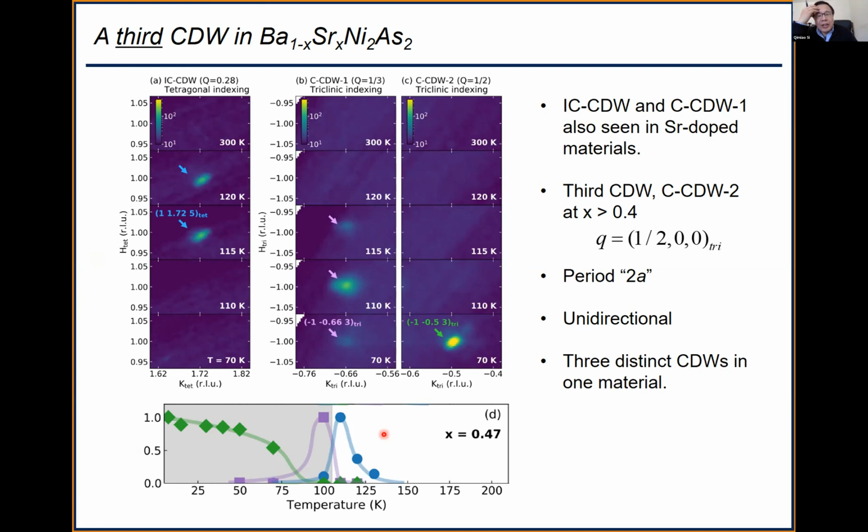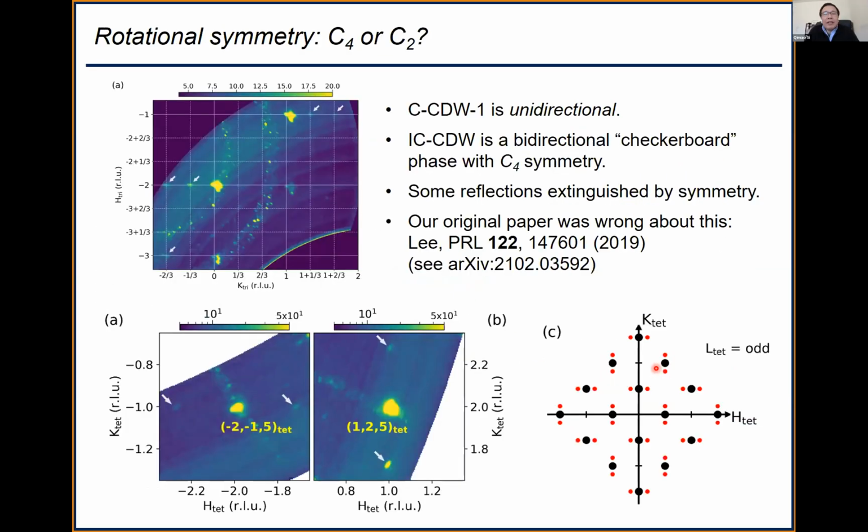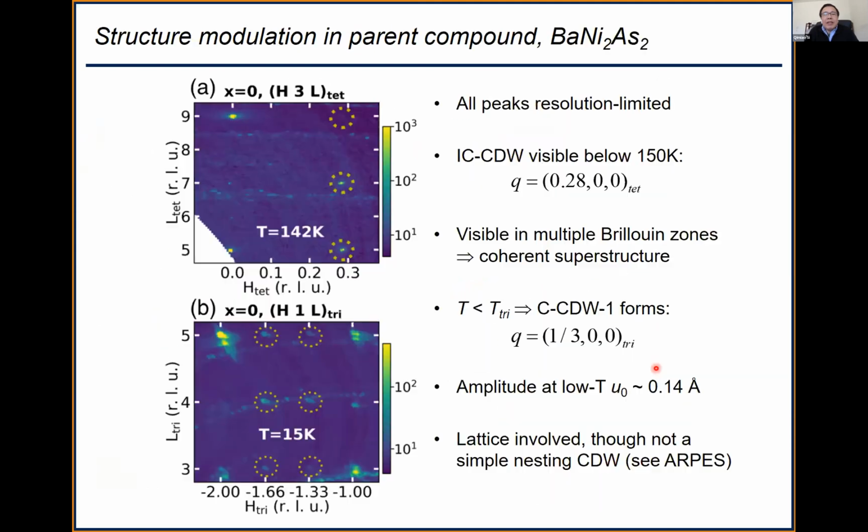So in the spin sector, one can say, I get the total spectral weight of the fluctuation to be, say, 5 Bohr magnetons squared per ion or some such number. In the charge sector, it's the same. That's the way to calibrate. Yeah, we did that. You can get that from an energy-integrated measurement. This statement came from the analogous thing in the charge sector. So what you get, instead of the local moment, is the local displacement amplitude of the structural distortion.